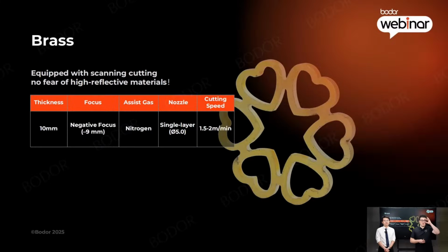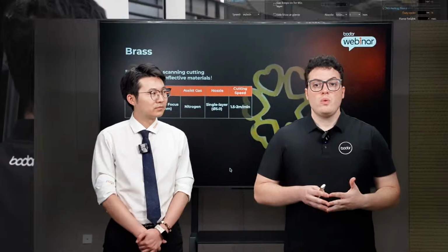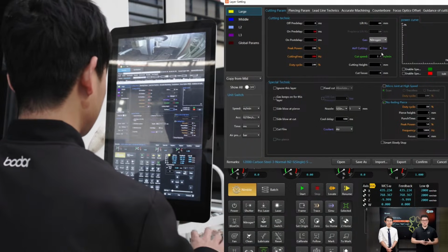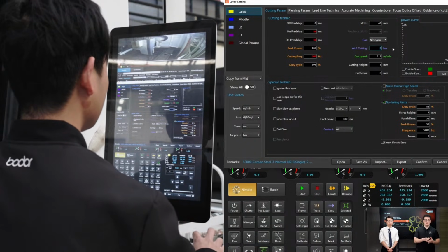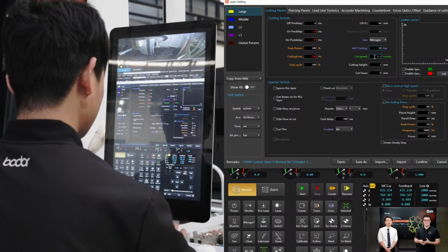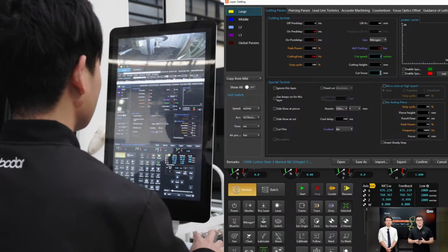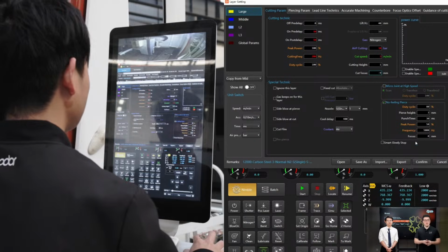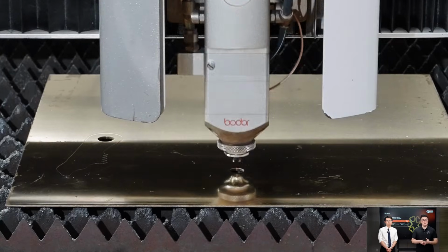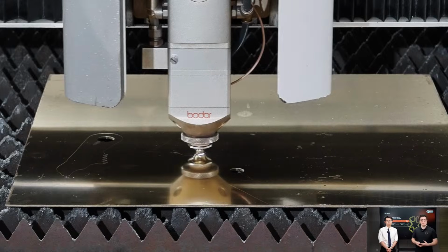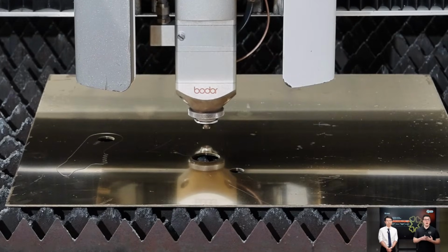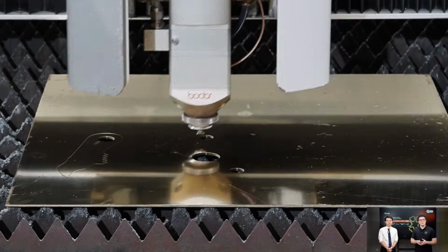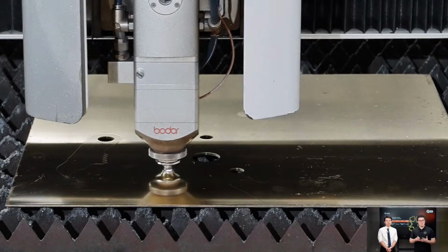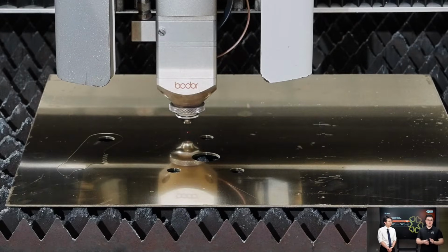This one is always a crowd favorite. Shiny, smooth, and full of color. We are cutting a 10mm brass sheet using the same 6 kW setup with the scan cut laser head, a single layer nozzle of roughly 5mm in diameter, a negative focus of about -9mm, and nitrogen as the assist gas. Brass under a higher power laser always looks stunning, especially when scan cutting is handling that highly reflective surface.